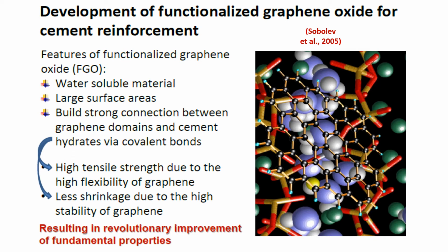Graphene oxide, GO, as everybody knows, can be prepared by the conventional Hummers or modified Hummers method, and it is one of the bulk procedures to synthesize graphene-like material by wet synthesis or chemical synthesis. And it has characteristic oxygen functional groups like keto, epoxy, or carboxylic groups on its surface. By virtue of that it is quite water soluble and can interact by hydrogen bonding.